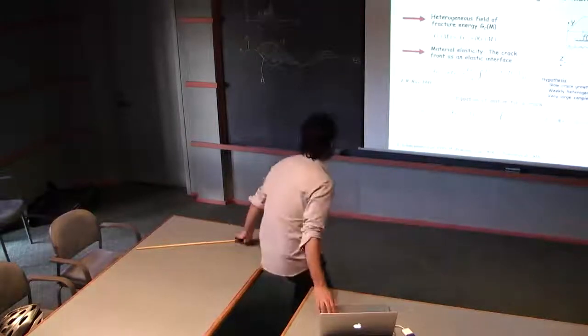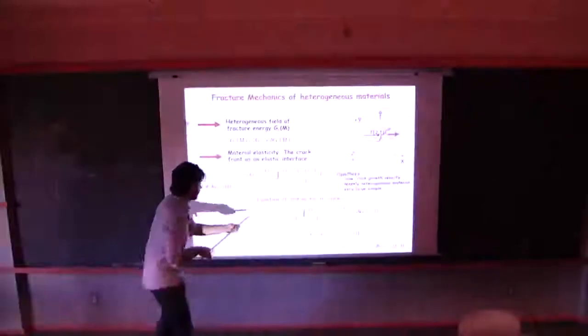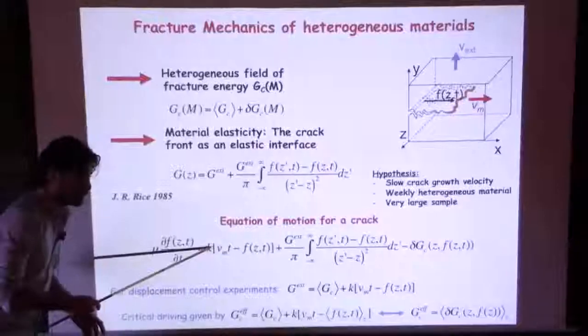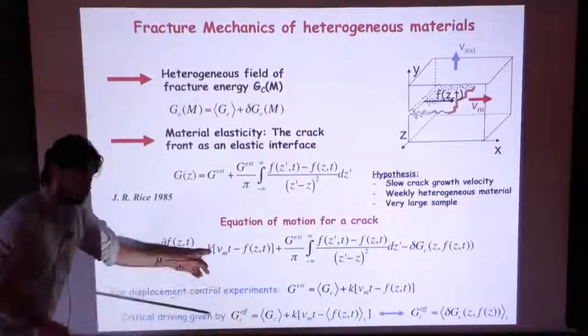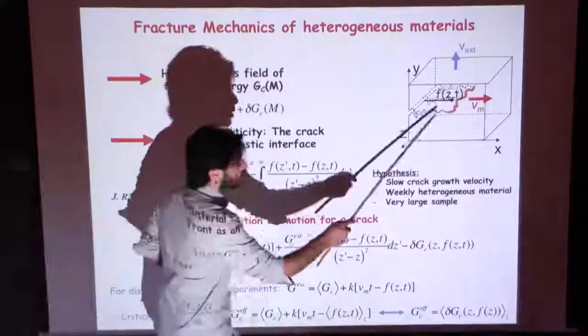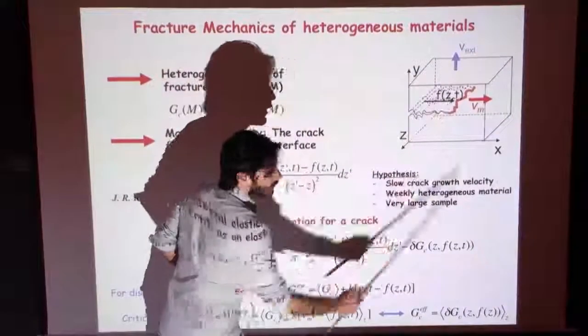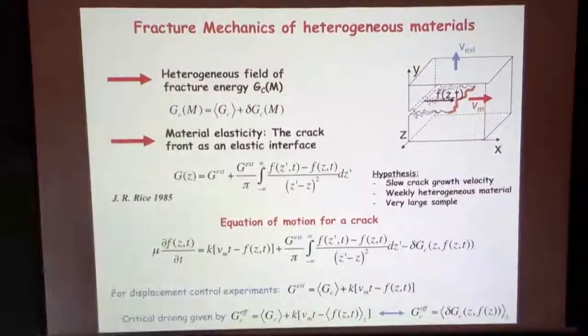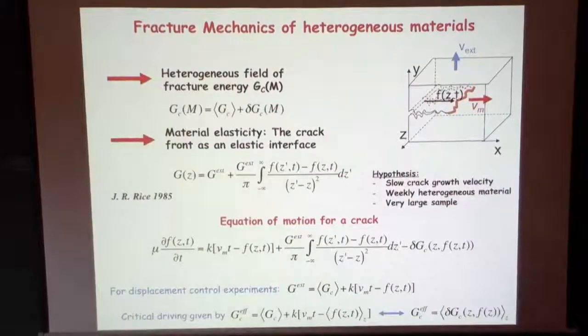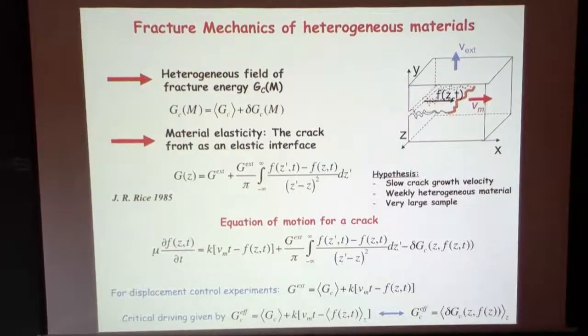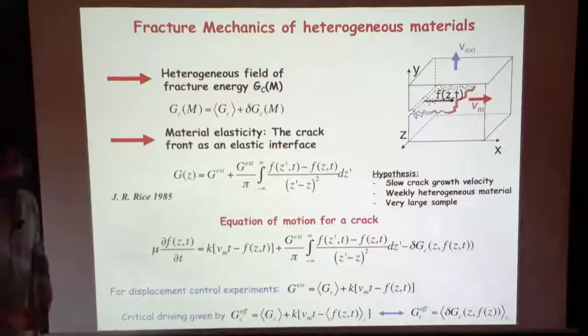Even simpler, since some of you know well the equation of evolution, the length scale that is important is this one. This is 1 over length scale. This is provided by the loading. It's a length scale coming from the loading condition and the geometry, typically the total crack length. This will set up a cutoff on your fluctuation. That might be of the size of your sample. That's why it's not so easy to neglect this fluctuation.